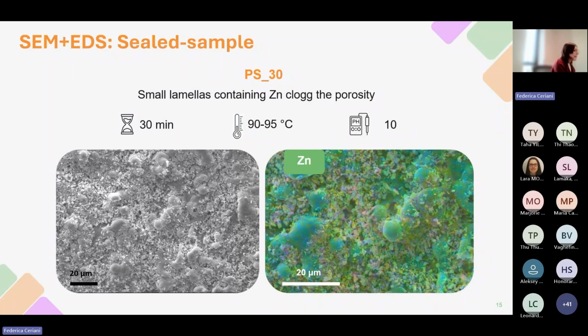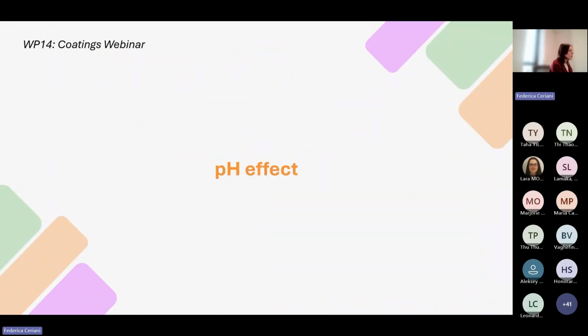By looking at the SEM and EDS images, we could note that small lamellas, mainly containing zinc, are spread all over the oxide surface, and these zinc-containing precipitates successfully clog the porosity of the PEO coatings, providing a great sealing effect. Now let's consider the first working variable, that is pH.